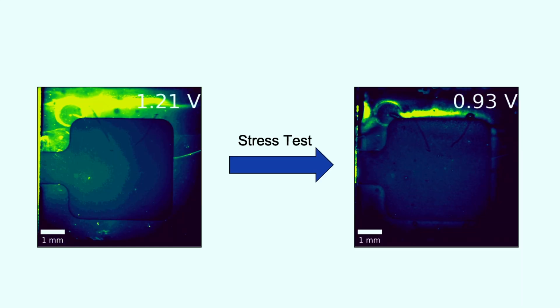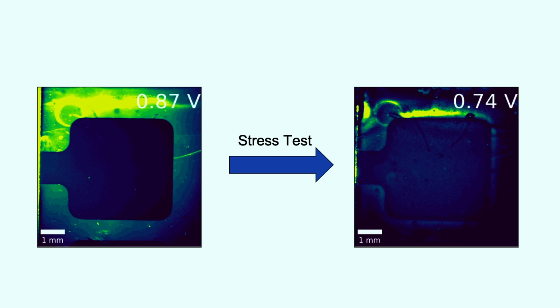So just a brief demonstration: this is a particular solar panel, and I'm shining some light on the solar panel and changing the voltage. And with this sweeping voltage, we're able to figure out that different regions operate at a much greater potential than others. If we then apply an accelerated stress test to the material, we can see that some regions also degrade very differently to other regions.